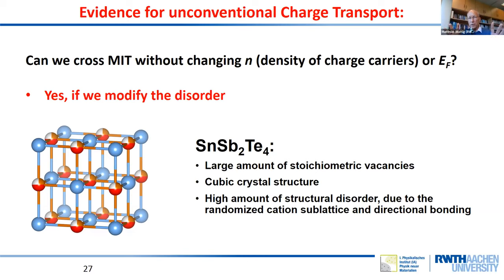And Mott argued you can do this by a correlation phenomenon. You reach a critical doping, for example, in phosphorus-doped silicon, and your system will become metallic. Anderson had a very different view. He argued, hey, there should be a disorder-driven MIT. And for 50 years, there have been lots of arguments pro and con the nature of the MIT in phosphorus-doped silicon, if this is governed by disorder or governed by correlations. And by now, almost giving up this kind of battle, people talk about the Mott-Anderson transition in phosphorus-doped silicon.